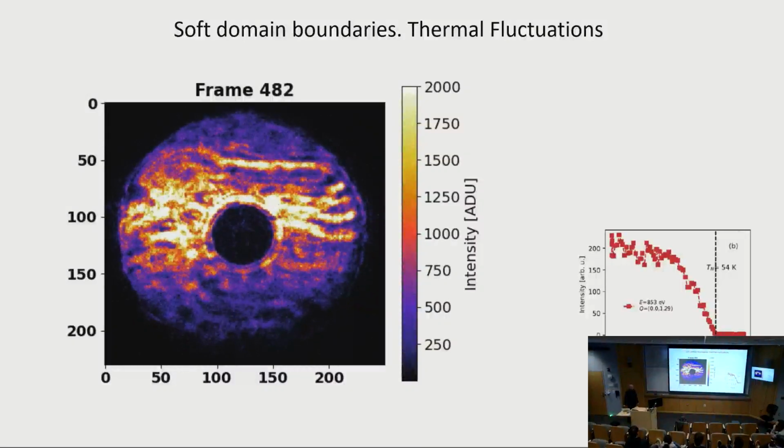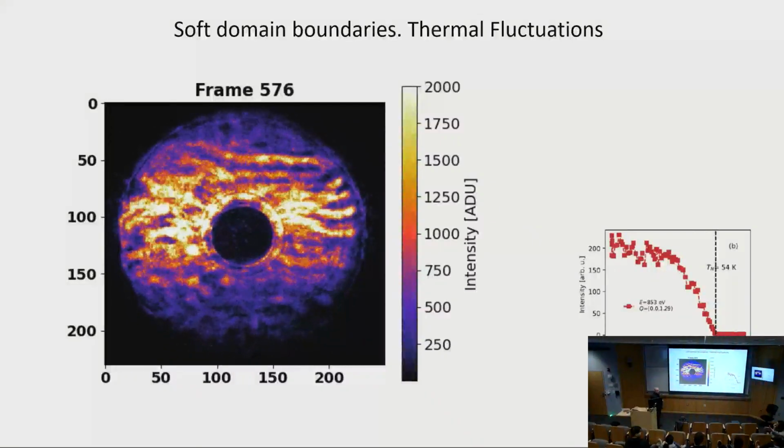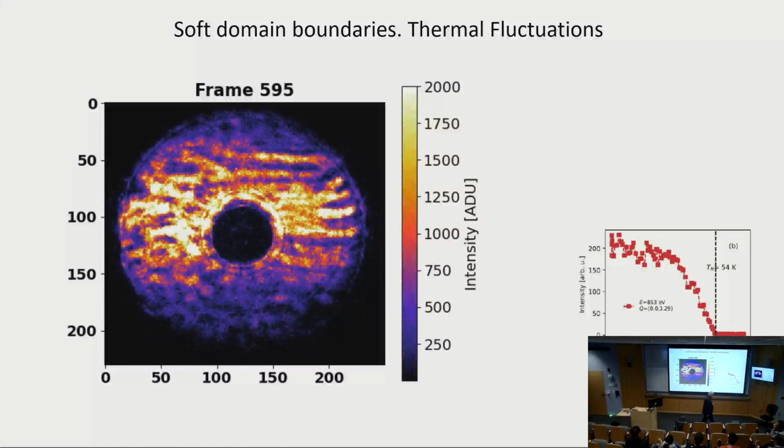Now there is a straight line here, as in zebra domains. Question? Yeah. How thick a region are we looking at? Yeah, so the experiments are done on single crystals, and therefore the thickness of the probed image is determined by the X-ray penetration depth. We are at a magnetic resonance, and therefore this penetration depth is small. In this particular geometry, I would say it's of the order of half a micron. This is the thickness of the probed region.